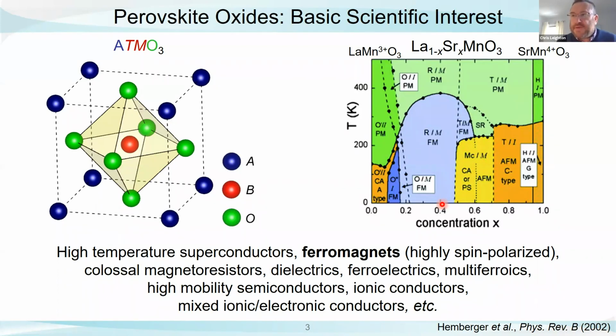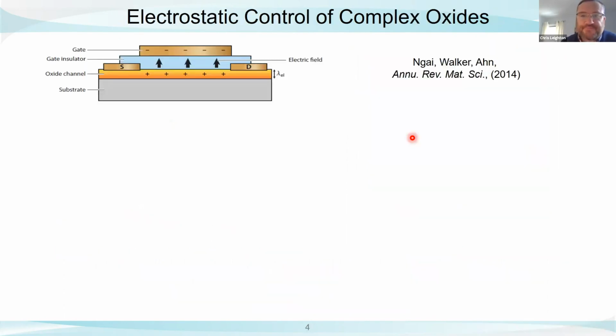So what I will talk about today is the concept that we could map a phase diagram like this using one sample, instead of the 20 or so that we used here. And if we were able to do that by electrostatically inducing that hole rather than chemically doping that hole, then we would have gained control over things like ferromagnetic Curie temperatures, antiferromagnetic Néel temperatures, insulator-metal transitions, and so on, which would potentially be of high interest for technology. So how could we possibly do that? Well, what I'm going to talk about today is a variant.